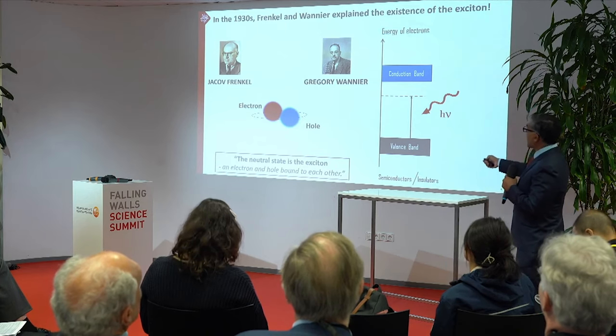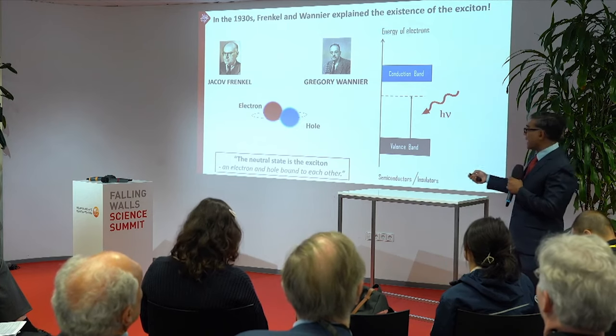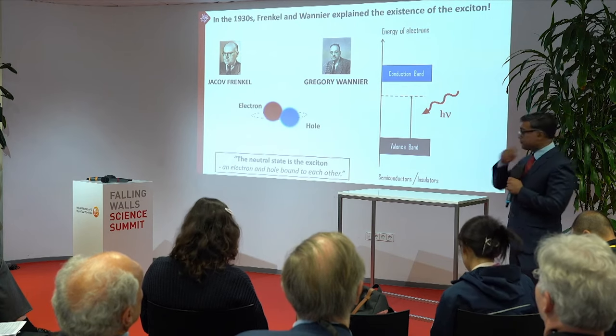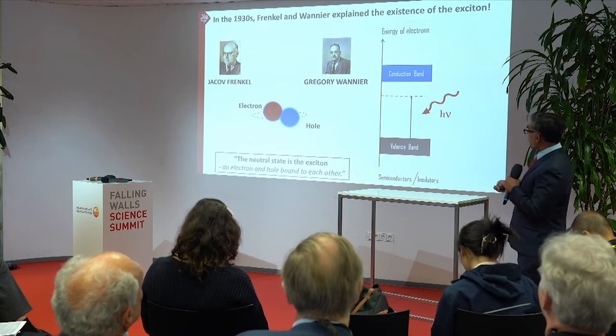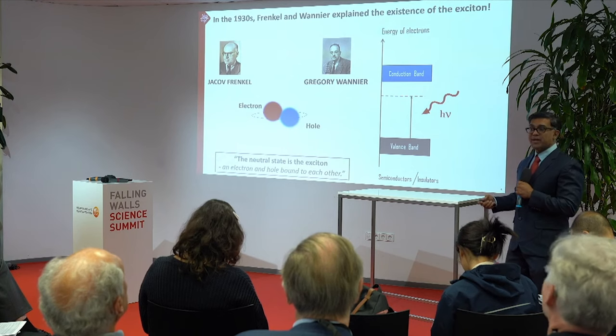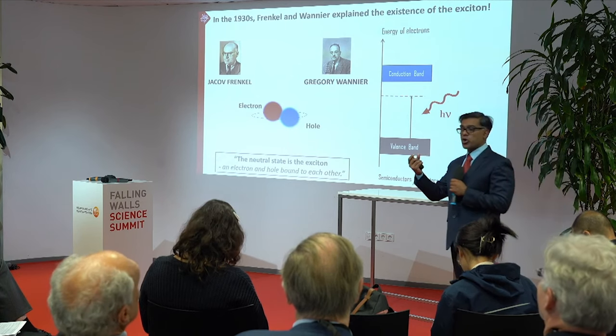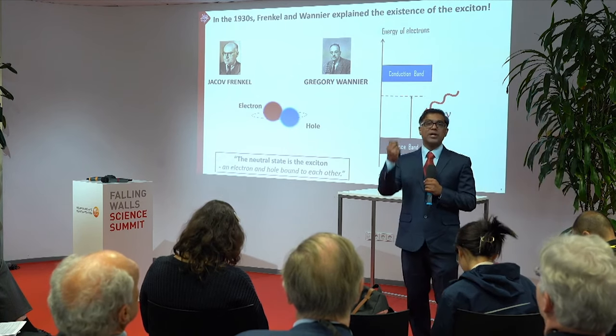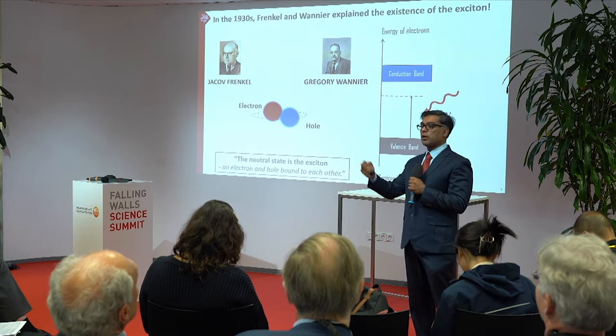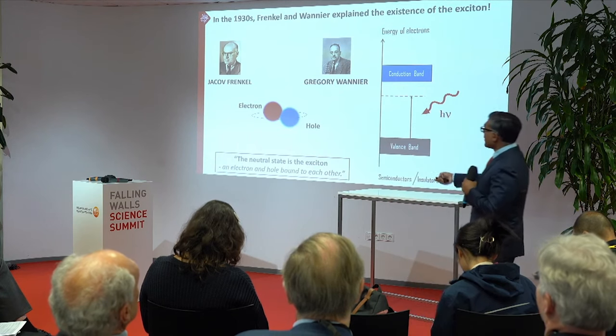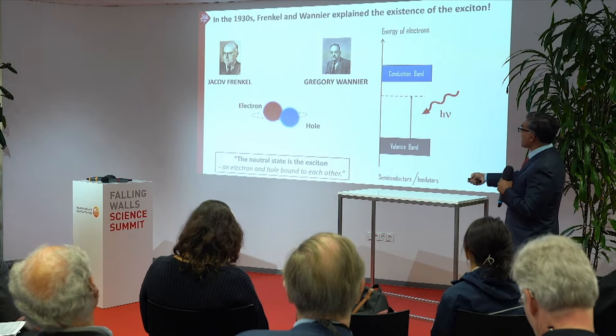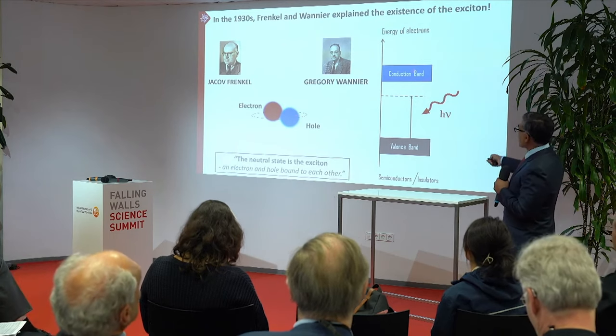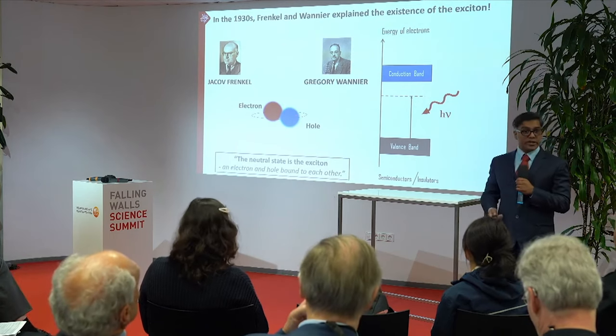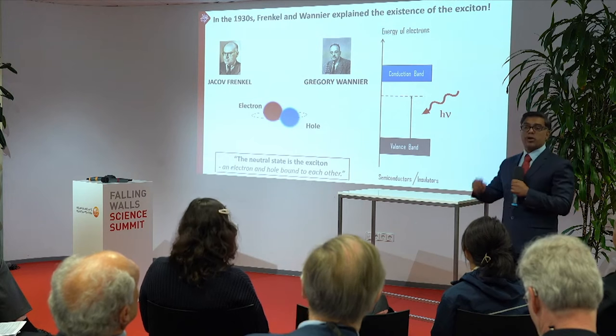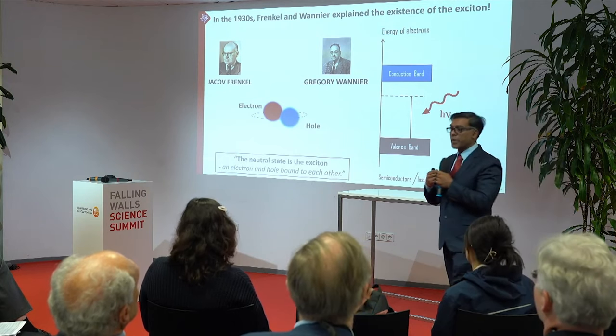Essentially, the electron that you create in the conduction band, which is negatively charged, is attracted to the hole that you create in the valence band. These two oppositely charged particles attract each other, forming a bound particle called an exciton. It's clear that because they're bound, the energy of the exciton is lower than that of the electron and the hole, so it lies in the forbidden region. And obviously it's neutral, because it's an electron and a hole bound together.